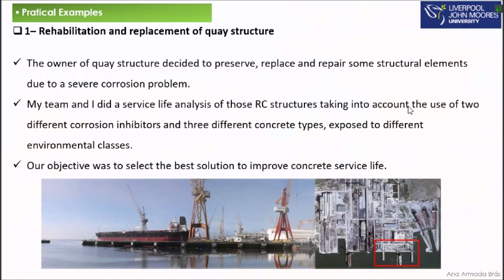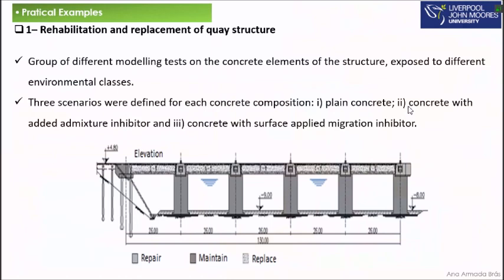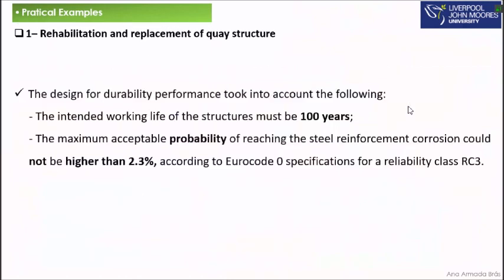Back again to the case study. So this is a quay structure, and of course we wanted to design the repair activities in order to ensure that the structure presents a target of 100 years. That's the working life that we expect. From European regulations, we know that the maximum acceptable probability of reaching the steel reinforcement corrosion cannot be higher than 2.3%. So assuming 100 years and assuming that the probability of failure cannot be higher than 2.3%, we